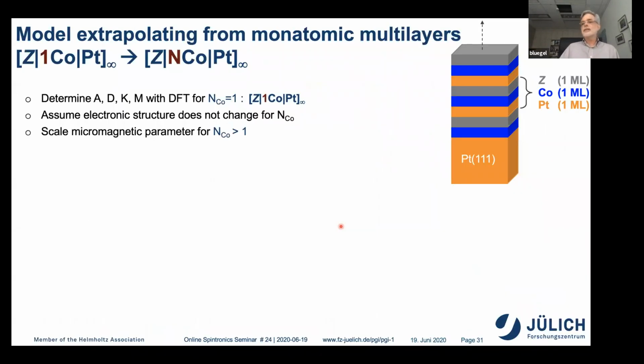Currently, we operate in a different way. So we say, okay, we calculate simple things. We calculate multilayers where each layer consists exactly of one layer. So it might be platinum, cobalt, and maybe ruthenium. And then what we do, we calculate these parameters A, D, K, the magnetization, with density functional theory for this cobalt thickness 1. And then we extrapolate by assuming that the electronic structure does not change. This is, of course, an assumption. And basically scale the micromagnetic parameters for larger thicknesses.